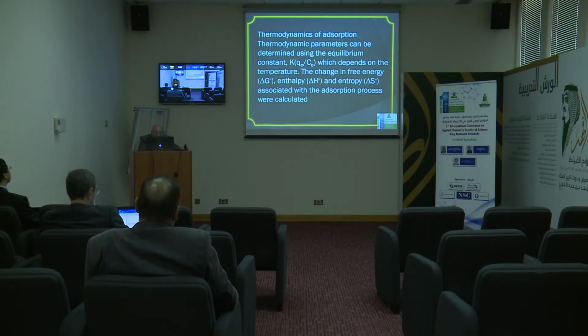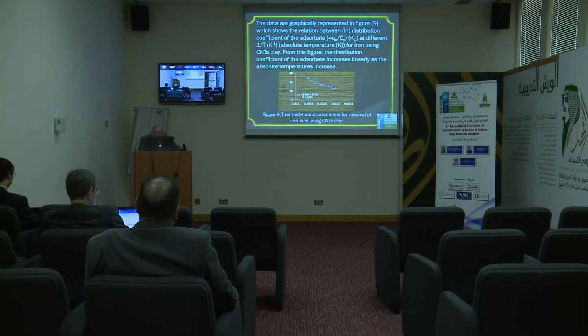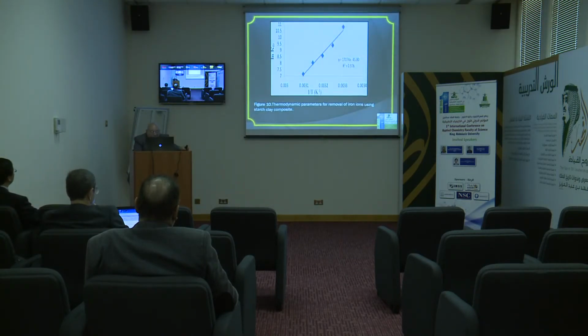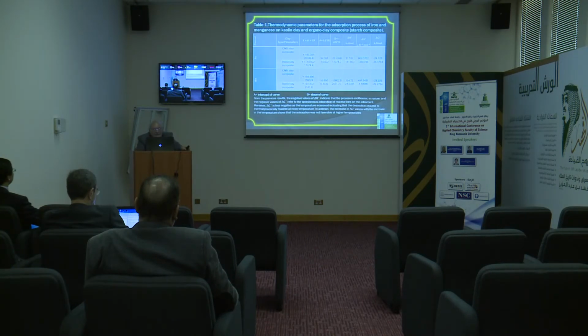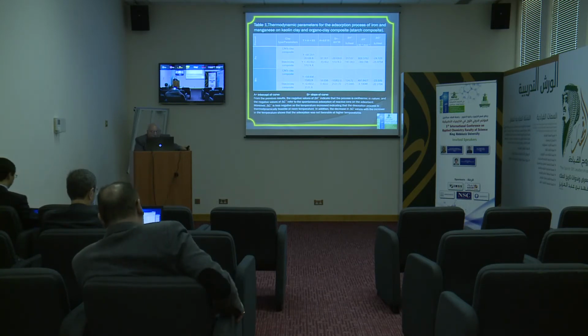Thermodynamics of the adsorption: thermodynamics can be determined using the equilibrium constants, so on, delta G, delta H. The data are graphically represented in the figure. I think this is the last one. Thermodynamic parameters for removal of iron using starch clay composite. This table illustrates the thermodynamic parameters for the adsorption process for different equations for both manganese and iron using the adsorbents used.